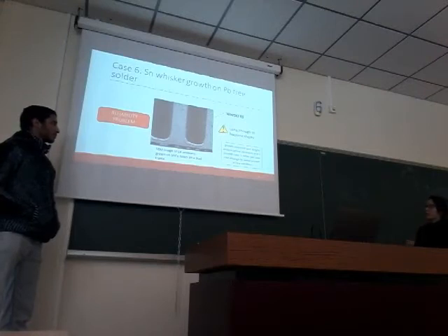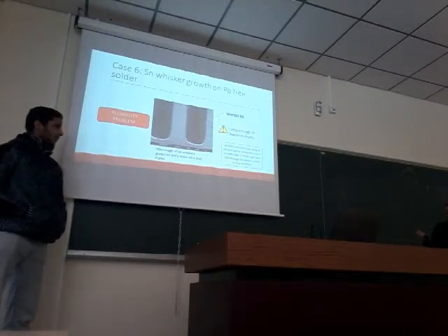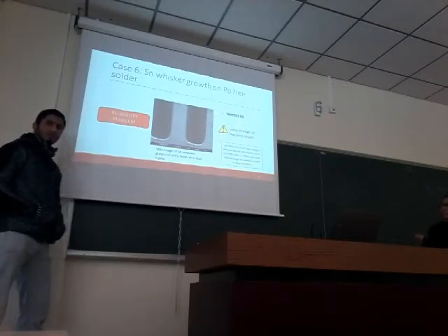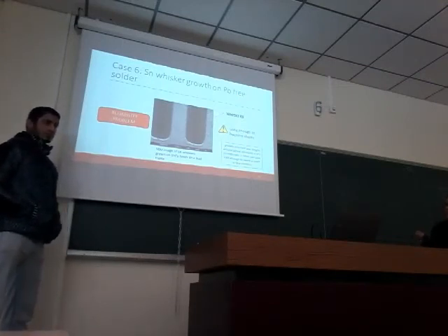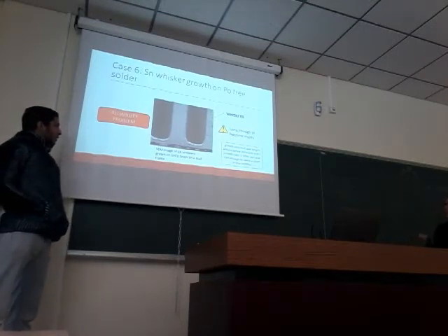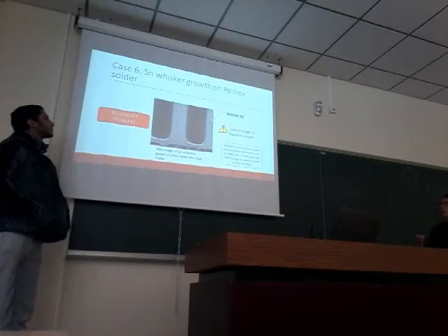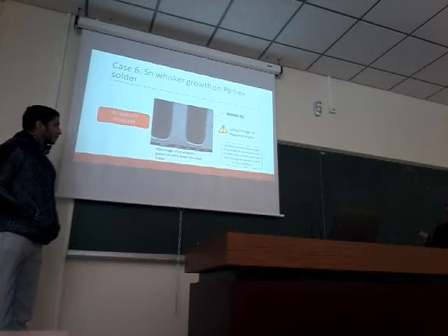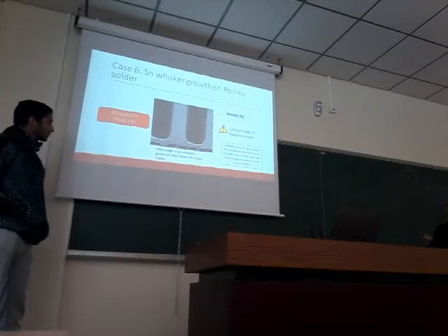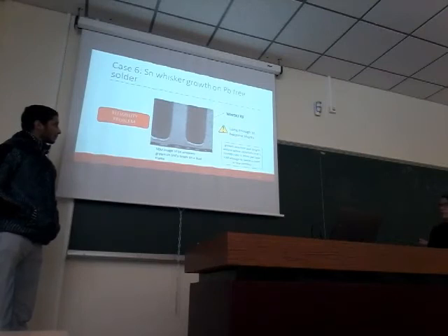And it has been observed that the growth direction and the length of the whiskers is around the lattice constant size. So the growth rate is about 0.3 millimeters per year, and the problem is that this is fast enough to cause a short circuit in a few months. As we can observe here, a short circuit can be created between the neighboring leads of the lead frame. So we are facing a reliability problem,